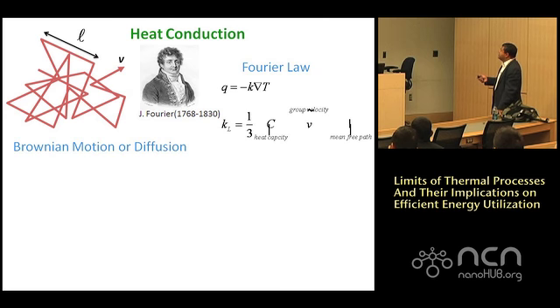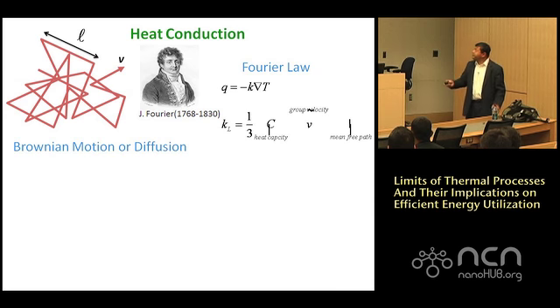Many of you know this: Fourier's law of heat conduction is taught at the undergraduate level. This heat conduction K comes from Brownian motion, essentially, of energy carriers. This motion is what we call diffusion. It has a characteristic length scale, a mean free path, which is the average distance a carrier goes before it scatters. It has a speed of propagation, and these carriers have a capacity to grab thermal energy. So if you put that all together, this becomes 1/3 CVL: the heat capacity, the group velocity, and L. This is the first level of peeling the onion from Fourier's law.